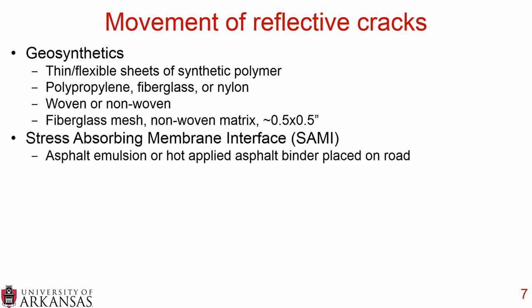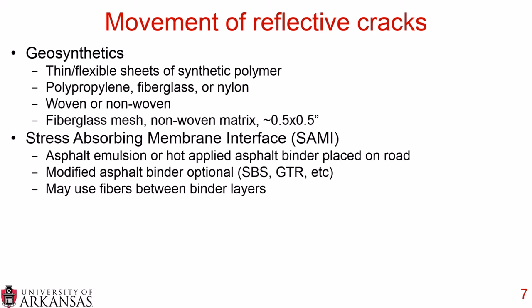Stress absorbing membrane interfaces, or SAMIs, are usually either asphalt emulsion or hot applied asphalt binder placed on the road, and you can potentially modify the asphalt binder with either SBS, styrene butadiene styrene, ground tire rubber, or other modification techniques. You may use fiber between the layers of asphalt emulsion or the hot applied asphalt binder, and you place coarse aggregate chips on top.